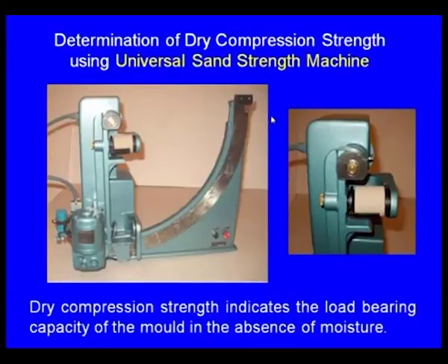Similarly, if we want to measure the dry shear strength, we have to change the pads. For measuring the dry compression strength and the green compression strength, the pads will be plain. For measuring the dry shear strength and the green shear strength, the pads will have projections on both the sides. Because of the projections, a shear will be induced.